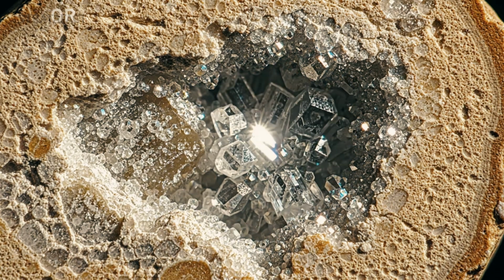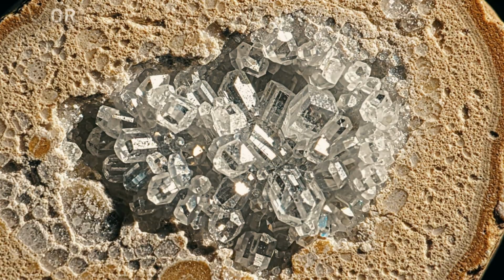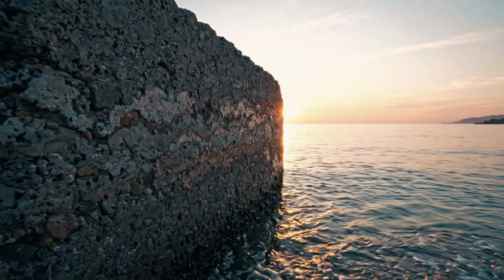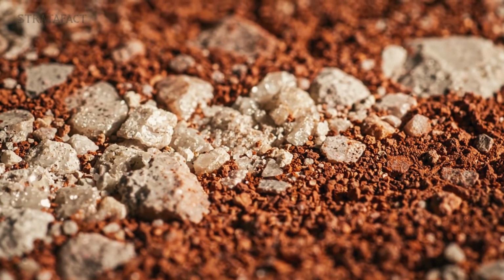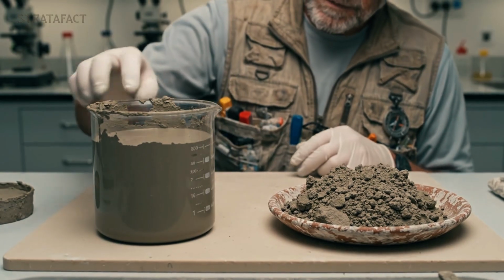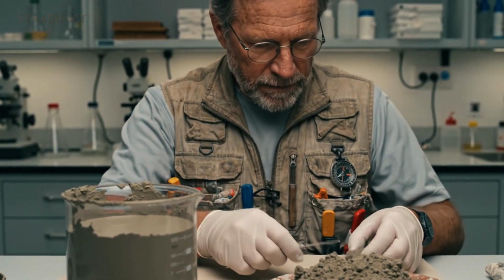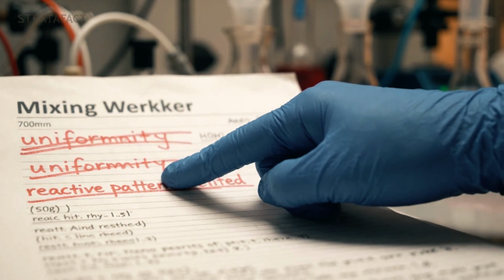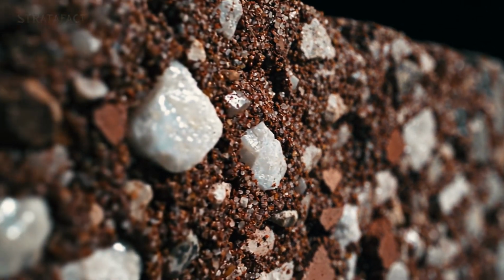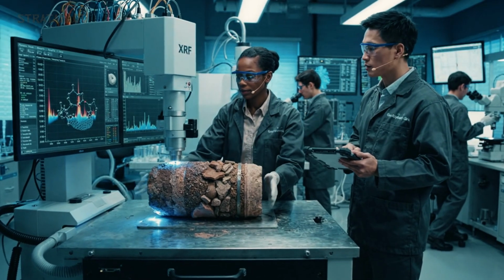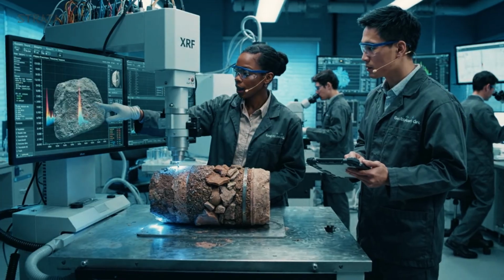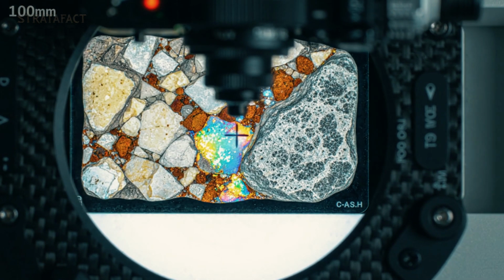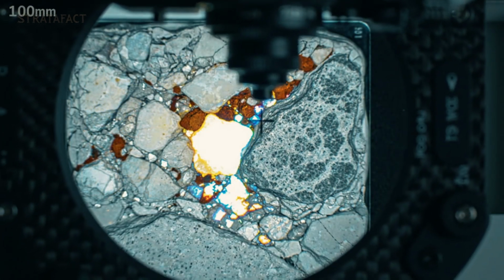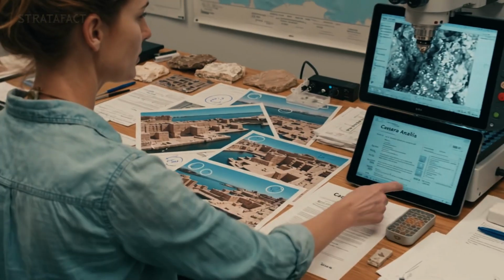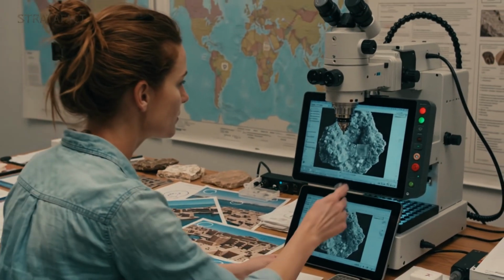The incompleteness of the original mix is the mechanism of the long-term durability. The durability of Roman marine concrete is partly a function of what was left undone in the mixing process. The material works not despite its imperfections, but partly because of them. The mechanism that produces tobermorite crystal growth requires the reactive lime to still be present as discrete particles in the set concrete, available to react with seawater decades or centuries after the initial cure. This is the kind of finding that materials science produces when it looks at ancient materials with modern analytical tools, not confirmation that ancient engineers were wiser, but identification of specific mechanisms that operated without the engineer's full understanding and that can now be deliberately engineered for.